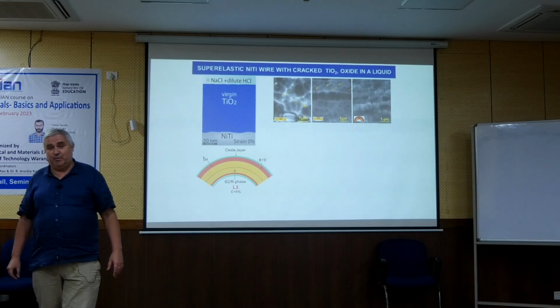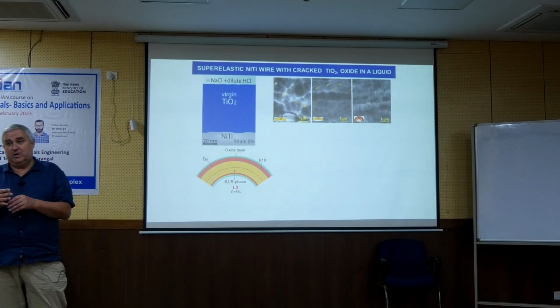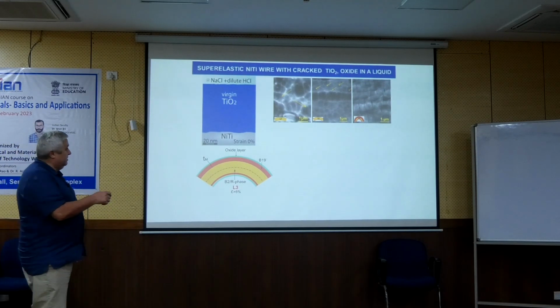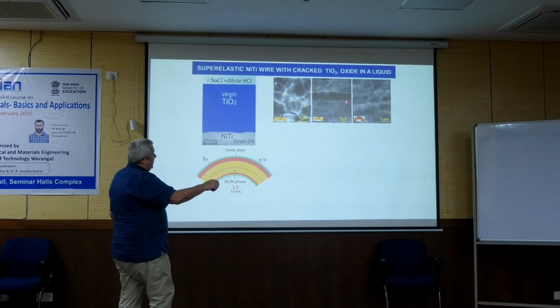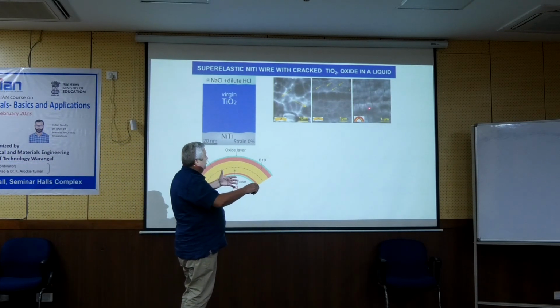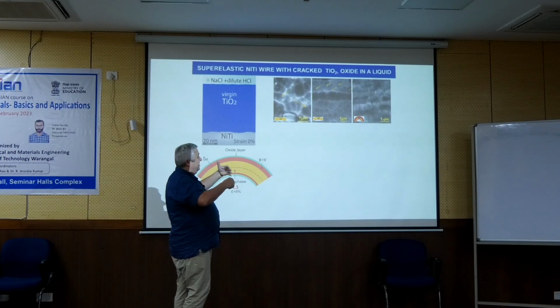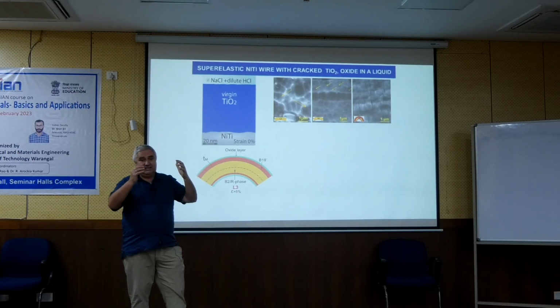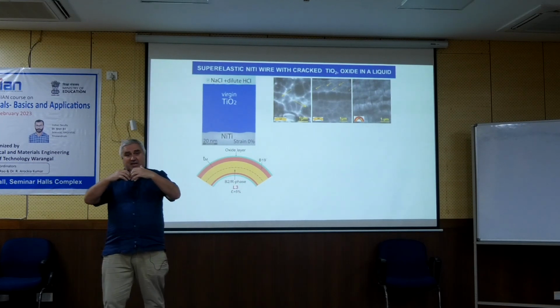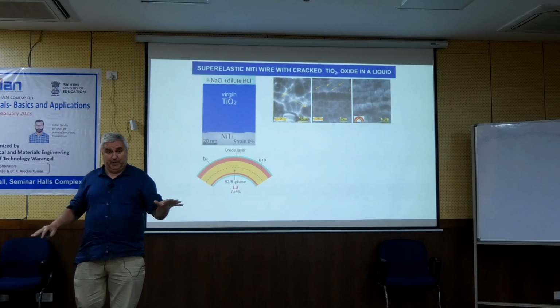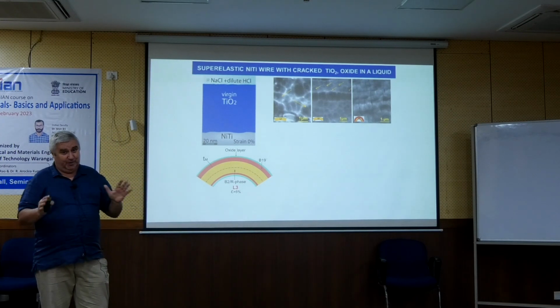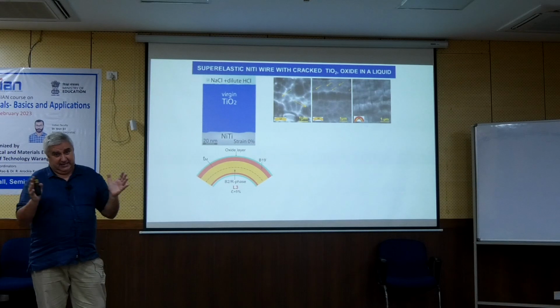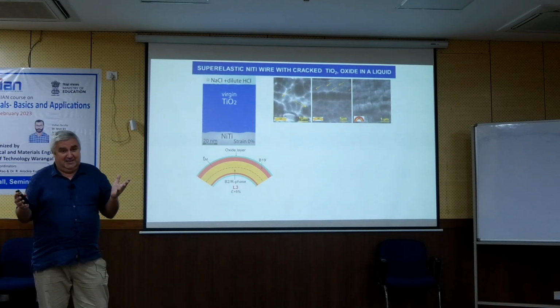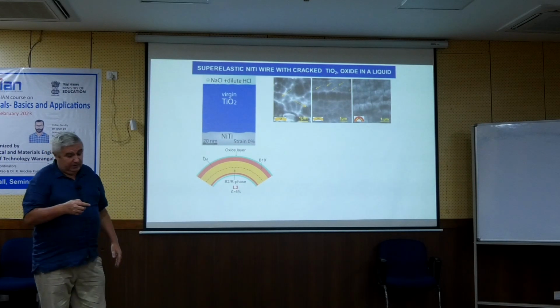So we thought that the source of the problem is not the crack itself, because when the cracks are exposed to biofluid, the healing process immediately starts. The cracks are filled by another oxide, and it's protected, and the problem is solved. So the material solves the problem when it's static. But when it is dynamic, maybe this was the idea. We didn't know.